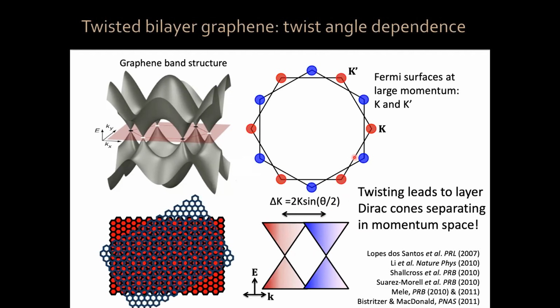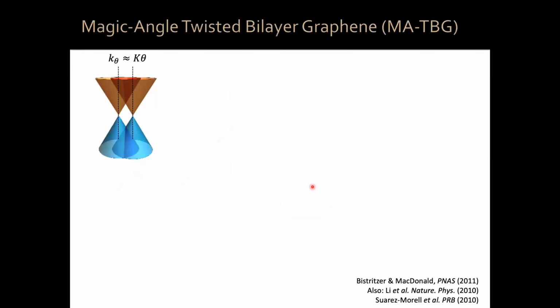Now, let's start from a small rotation angle such that the difference in momentum is proportional to the angle, because sine of a small angle is equal to the angle, okay? And let's see what happens. So now this would be the situation that would occur in the energy momentum dispersion for small angles, so that the separation between these points is proportional to the angle. But this would be the situation if electrons in one graphene sheet would not know about electrons in the other graphene sheet. However, these 2 graphene sheets are just 3 angstroms apart.